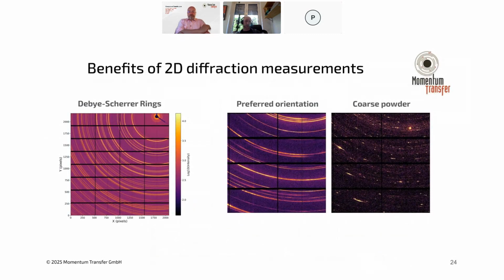Another thing that I mentioned is that we use the area detectors. And this is really beneficial because it allows you to collect a little bit more information about the sample, potentially, if it's not an ideal sample. So when you work in the lab and you have a point detector or position sensitive detector, basically you're just measuring on a point. And if you look at the image on the far left-hand side, there's a little black circle. And that little black circle is essentially the direction of where the incident X-ray beam is pointing to the detector.